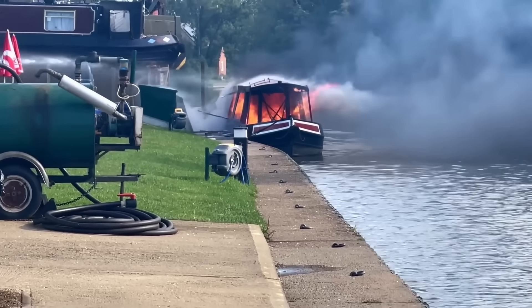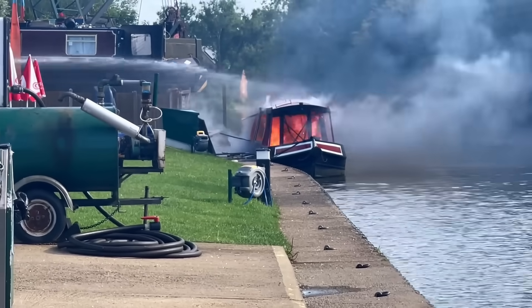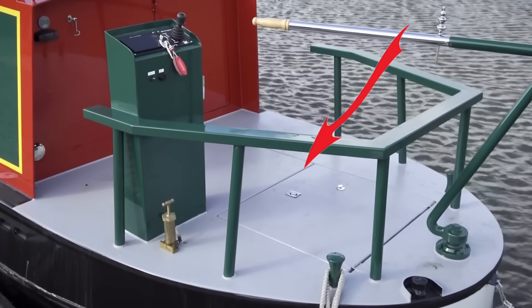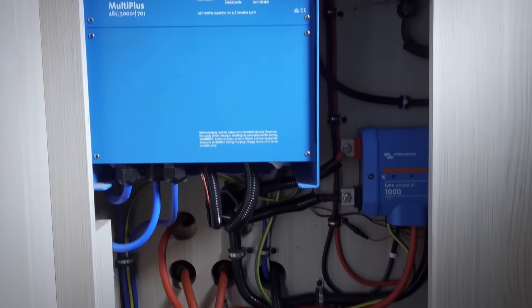On the morning of the 5th, the boat was on charge. Witnesses reported a large bang, followed by flames engulfing the cabin. Glass shattered, parts of the hatch blew off, and the fire spread rapidly. While the batteries were located in the stern, directly under that area, they had a path to off-gas, which allowed the rest of the structure to get consumed quickly. So how did that gas get into the vessel and cabin, and what ignited the mixture? If you look at where the electronics are located, you'll see large openings through the bulkhead for the wiring. A single battery failure would have off-gassed enough to make the atmosphere inside that battery compartment extremely rich with flammable vapor. But inside the cabin, that larger volume would have allowed the gases to mix into a perfect explosive concentration — it would only have taken a single spark from something as simple as a fridge to set the whole thing off.